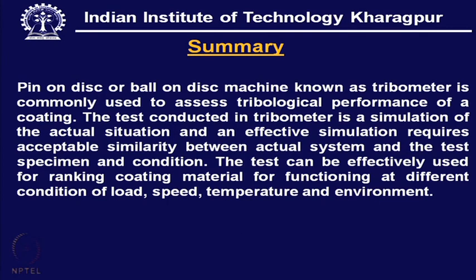So, with that we can make a summary of this discussion: the pin-on-disc or ball-on-disc machine, known as a tribometer, is commonly used to assess the tribological performance of a coating. The test conducted in a tribometer is a simulation of the actual situation, and an effective simulation requires acceptable similarity between the actual system and the test specimen and conditions. The test can be effectively used for ranking coating materials for functioning under different conditions of load, speed, temperature and environment.